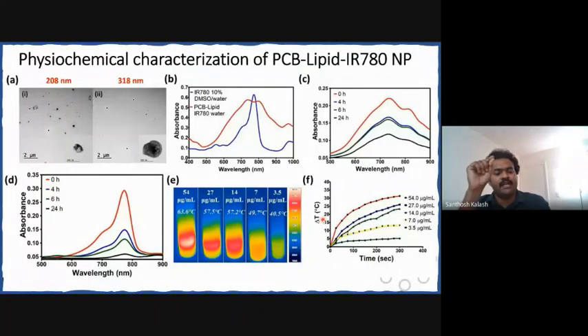But when we loaded the nanoparticle with IR780 dye, the size slightly increased, by around 100 nanometers. We can also see that the core is a little bit darker, which means that the dye is getting aggregated within the nanoparticle. So we confirmed that the nanoparticle is formed and the dye is inside these micellar nanoparticles.